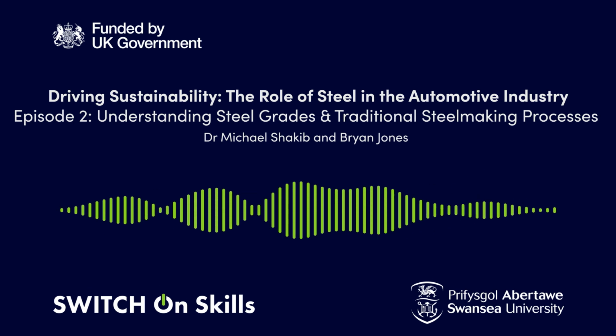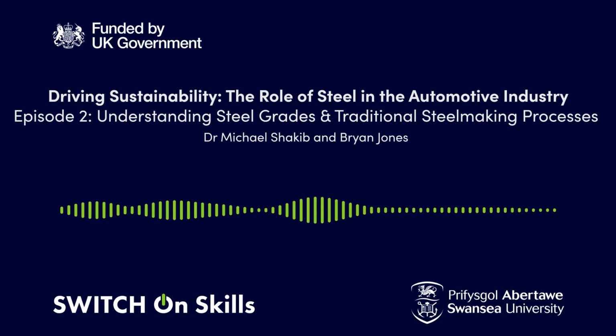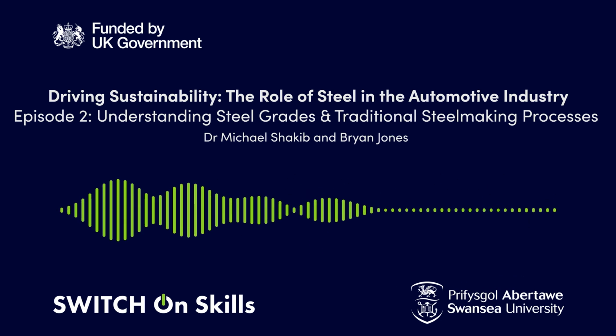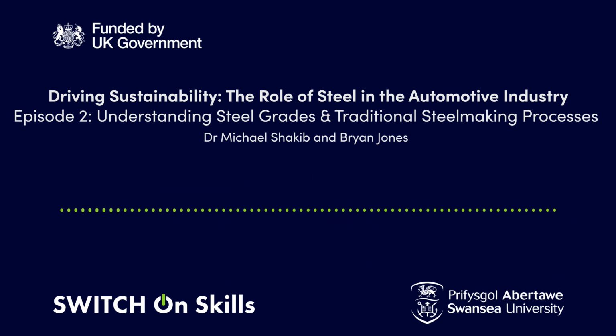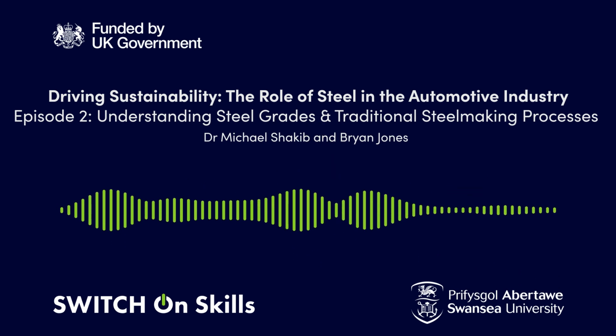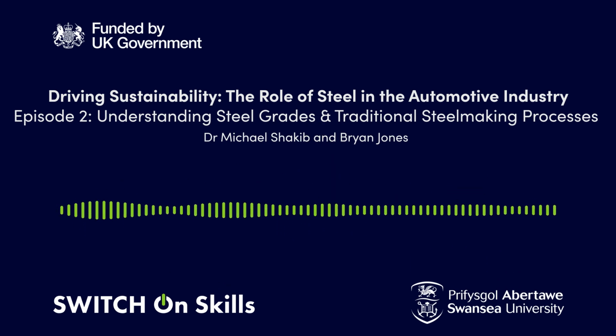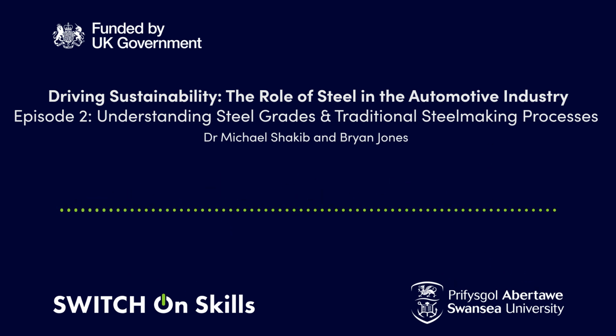Strength is more limited, of course, because you've now achieved this high level of formability, but you have to accept the fact that for certain applications in a body structure, where you've got a highly complex geometry, you ain't going to use a dual phase steel for that. No. You've got to have a lower strength product to achieve the performance you require. Bake hardening steels then, of course, come into their own, where you've got very good formability, not as good as, say, an interstitial free steel. Yeah, and we talked about bake hardening steels already, haven't we?